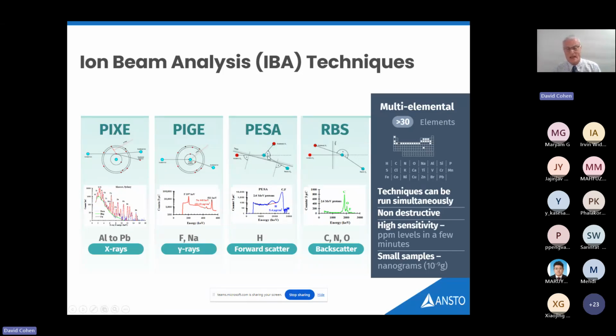And this is one of the few techniques that's very good for measuring hydrogen, because hydrogen is the lightest element of the periodic table, and therefore it's well separated from other ones. So when you get your spectrum, you get a peak for hydrogen, whereas carbon and fluorine, for instance, sort of overlap, so you don't get element resolution, but the hydrogen is very good.